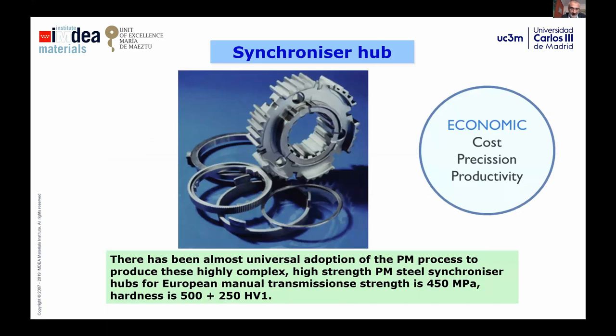Second, one example of this field of application is the synchronizer hub. Synchronizer hub is a very interesting part. It is part of the transmission of one conventional car, and in each transmission you have at least 5 of these synchronization hubs. This part usually was made in the past, maybe more than 15 or 20 years ago, by forging and machining. By this alternative method, the cost to develop this part is in the order of 40-50% more than by powder metallurgy. By powder metallurgy, you can develop the part with enough properties to fulfill the requirements of the transmission of the car and at much lower price.